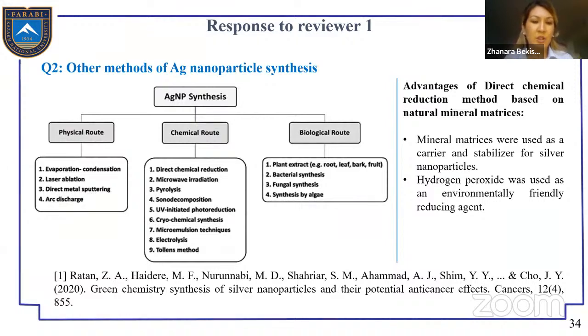This is with the wet reduction method, UV or gamma irradiation, and bacterial synthesis in biological methods, and the advantages of direct chemical reduction, which we chose. It is the synthesis of this composite. The mineral matrix was used as a carrier and stabilizer for silver nanoparticles, and the environmentally friendly reducing agent is hydrogen peroxide.